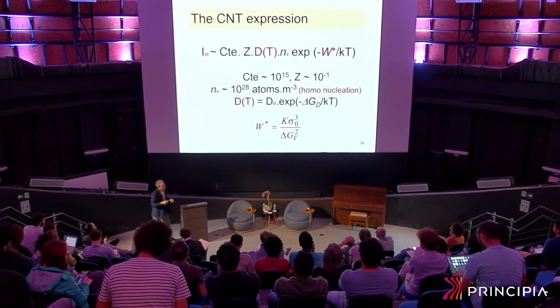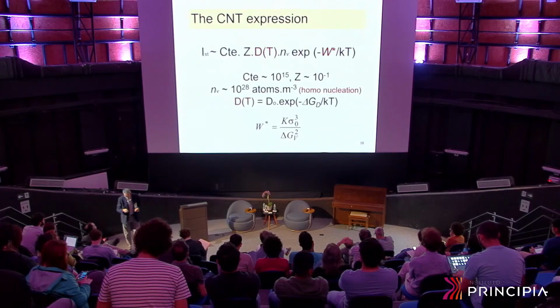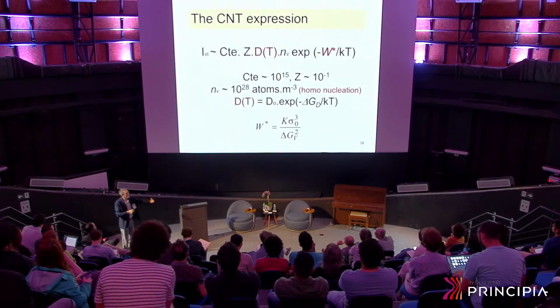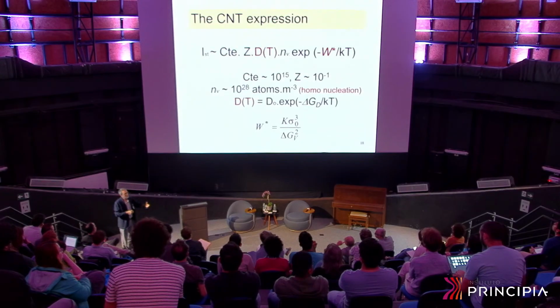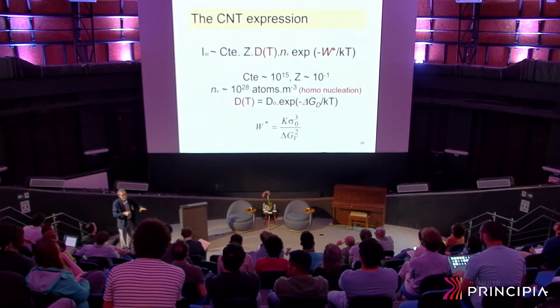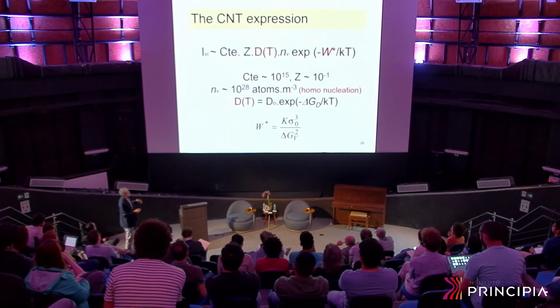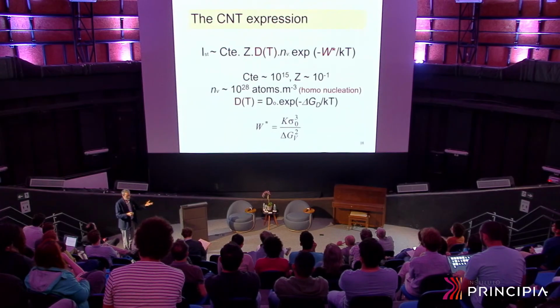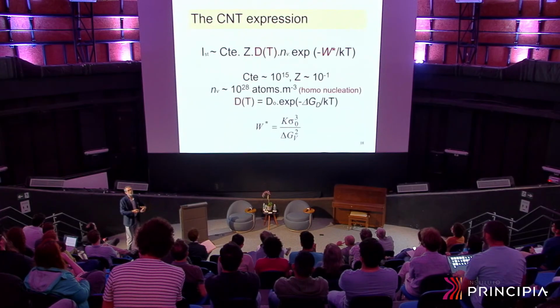This classical expression is very simple and elegant. It shows that this is the rate, the number of critical nuclei that form per unit time, per unit volume. The unit is like crystal nuclei per cubic meter per second. This is the nucleation rate at a given temperature.